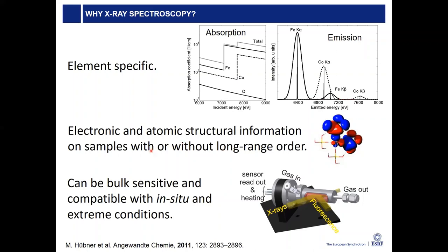What is very important is that you can do this on samples with or without long range order. If you do a diffraction experiment, you need some kind of long range order. And this is not required in spectroscopy. That's an important point. So if you have samples, for example in environmental sciences, you just want to put a piece of soil and see what the chemical state of whatever is inside the soil is, you don't need the long range order. Any amorphous or polycrystalline sample you can put in the beam and get a spectrum out.